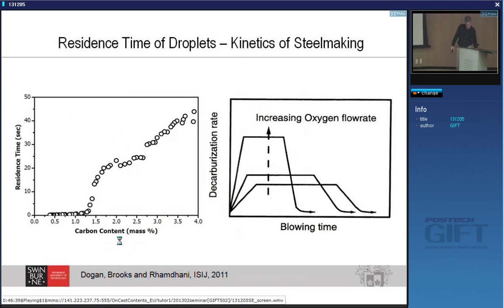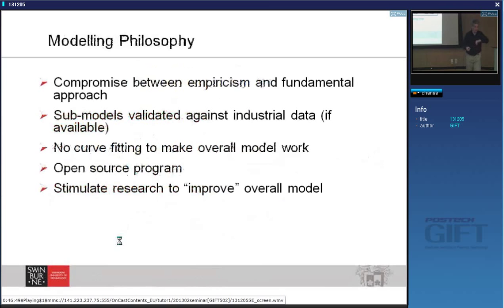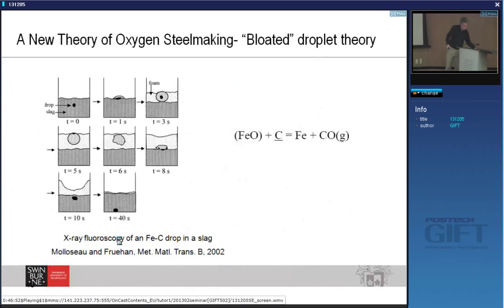In the emulsion, we had to develop new theory about how oxygen steelmaking works. And I want to explain to you where that idea comes from. If you look at experimental data on oxygen steelmaking, if you put a droplet of iron into a slag, the droplet doesn't just sink like you would predict. The droplet actually bloats, because the gas from decarburization cannot escape. Actually, it's very similar to when you put an aspirin into water, and you see the bubbles raise the aspirin. This behavior means that the residence time of droplets is very high when you have a lot of carbon to get rid of.